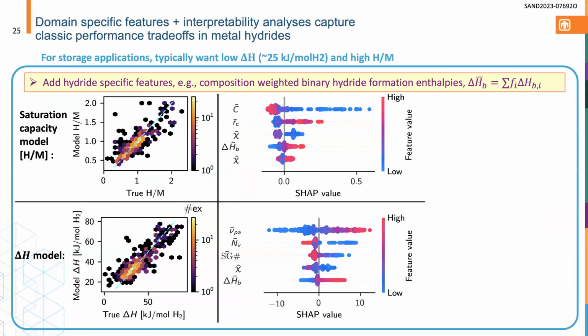Okay, so if you click again, I want to dive into these SHAP analyses briefly. So we added in some additional hydride-specific features. If you take the binary hydride formation enthalpies computed from DFT, you can well define this new descriptor for any new composition. And besides just predicting the log equilibrium plateau pressure, we can predict different properties of metal hydrides too, right? So we can predict their saturation capacity on a hydrogen to metal basis, and we can predict just the enthalpy, right? So now we're ignoring entropy for the moment.